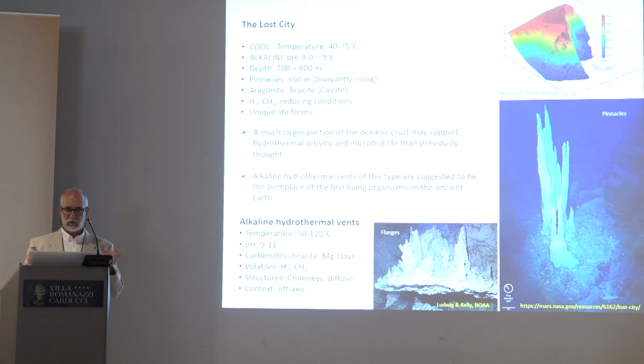But the environment was completely different. The solution was cold, 40 to 75 degrees, and the pH was not acidic but alkaline, 8, 9, 10. There were also volatiles, but the main volatiles in this case were hydrogen and methane. And the images were spectacular, in the sense that there are no plumes, but fantastic white towers formed of aragonite and brucite, and calcite coming from the aragonite.